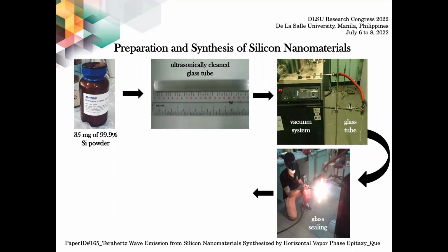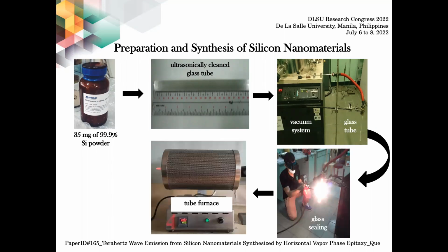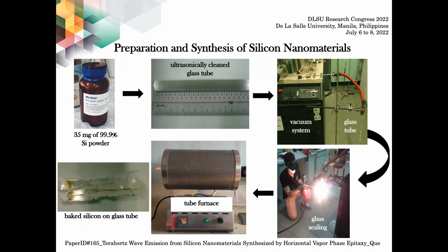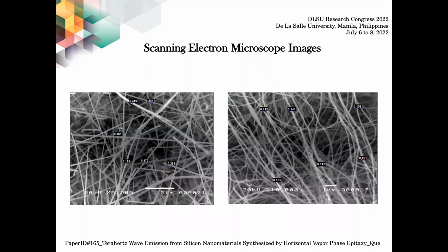The vacuum-sealed glass tube was then placed horizontally in a tube furnace and baked at 1,200 Celsius for 7 hours. This is the image of the glass tube with silicon nanowires after baking. Surface morphological measurements of the baked sample reveal silicon nanowires at 5,000 and 10,000 magnifications, respectively.